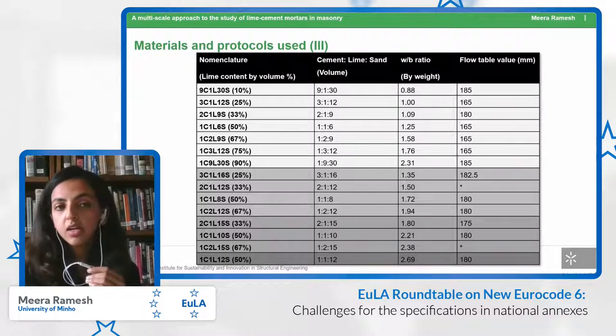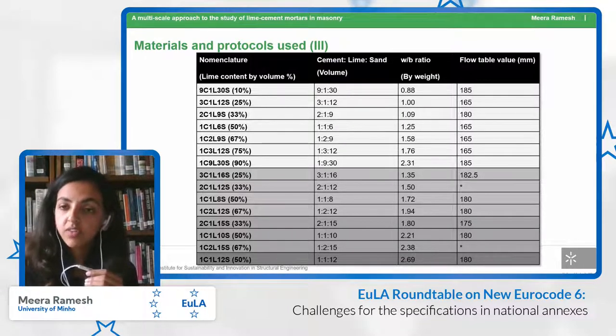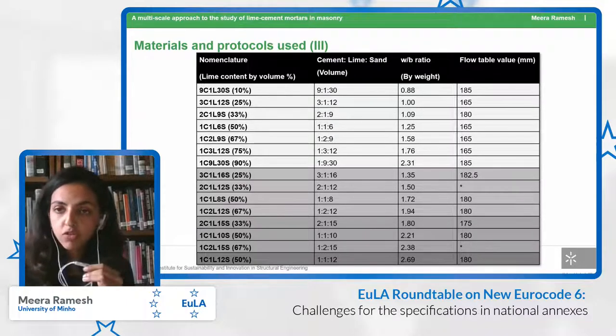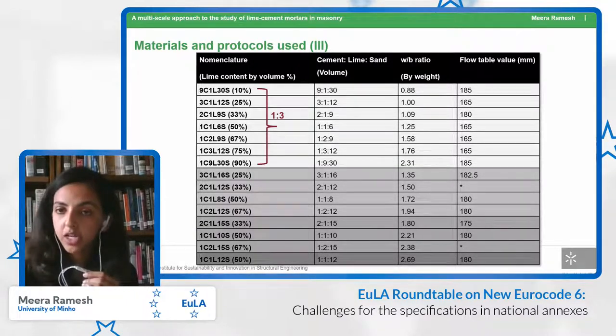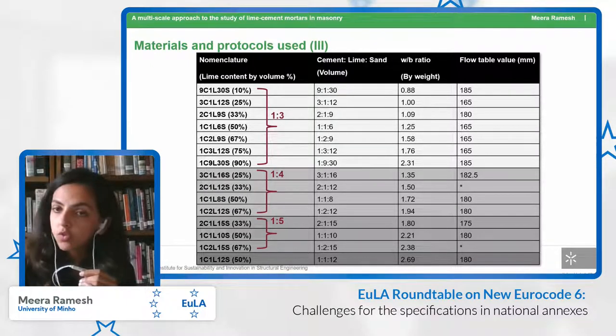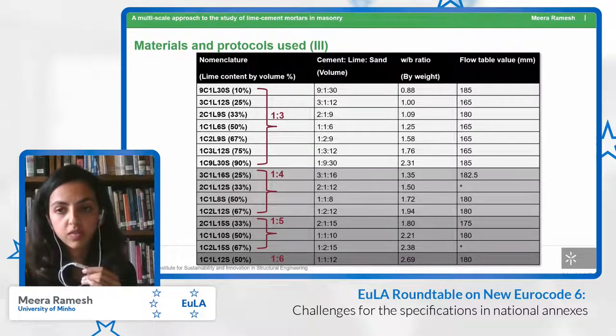For the mortar level study, at least for the mechanical strength, we had 15 different mixes, and we studied them at 6 different ages, from 7 days to 365 days. The rationale behind selecting these mixes was to study a wide range of lime cement ratios, but also different binder aggregate ratios. So we studied 1:3, 1:4. We had a few mixes for 1:5, and finally 1:6. The water binder ratio for every single mix was determined such that it would result in a flow table value of 175 millimeters plus minus 10.